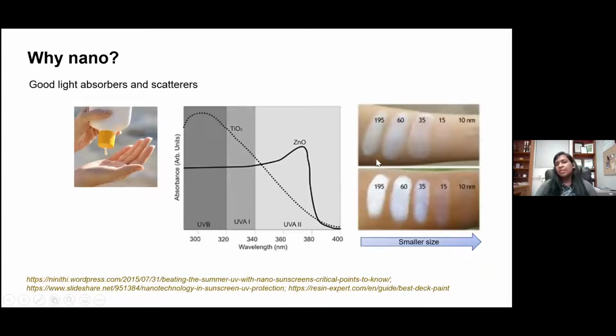So here we see nanoparticles of different sizes as they're applied to skin. So when these particles are larger, they can absorb into that visible and kind of scatter a bit more light, so they appear white. And we don't like that white color when we apply sort of the sunscreen. We want that to go on clear. So if we actually make these nanoparticles smaller, so in the 15 to 10 nanometer size, they actually reflect that visible light very well and only absorb UV, and therefore they appear clear when we apply it on our skin. So by tuning the size, we can actually tune which light it absorbs and which light it reflects or scatters better.